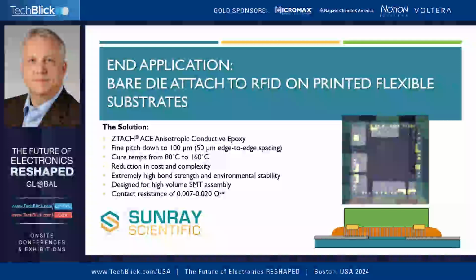And the goal was to be able to cure this at relatively low temperature. As I said in the previous slide, we can cure ZTACH in our standard formulation anywhere from 80 C all the way up to 160 C. So it works on a pretty wide range of materials. They wanted a reduction in cost and complexity, meaning the other solutions that they were going to have were probably going to involve an underfill and encapsulation, or at least one or the other. They needed very high bond strength and durability to withstand the packaging and the processing, as well as just the transportation of the parts that these tags are going to be put on. It had to be designed for high volume and ideally designed for existing manufacturing processes. So a drop into existing SMT line process was ideal.